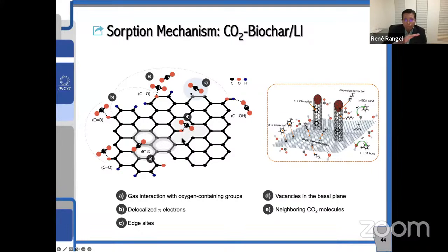This is when we have a graphitic layer. But then remember that we are growing carbon nanotubes, so CO2 will also interact directly with the carbon nanotube. We have more area, but we also have more active sites. We have the graphitic layer, in this case in the form of a tube, but it still will give a lot of active sites to remove CO2. Okay, so the mechanism is not simple, but there are different ways in which this molecule can interact with the surface of these materials.